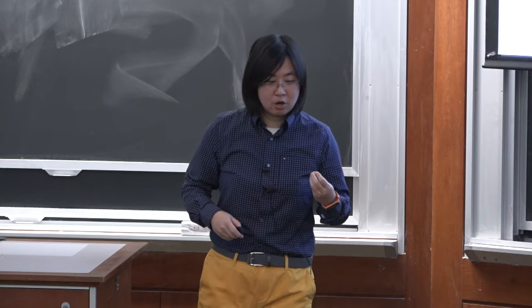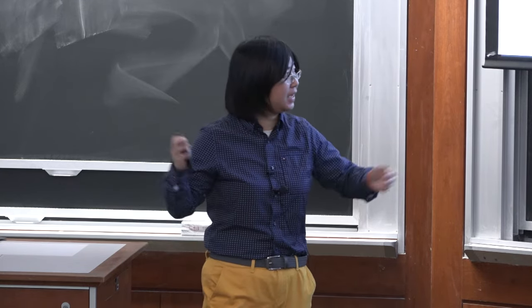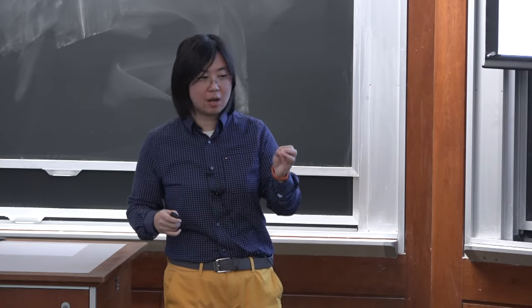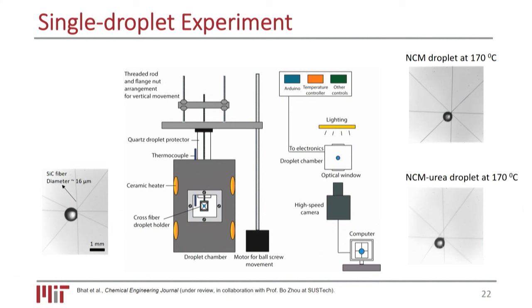And in order to understand that, we go back, stay away from the lab scale big experiments and try to look at what happens to a single droplet inside the chamber. Remember, I said in the precursor stage, we spray the droplet into a chamber and control its heating process. So we mimic this heating process by using this chamber. Inside this hot chamber, we can control the environment, and we have a holder where we put, I'm not sure if you can see it in the back, very, very thin silicon carbide fibers, and suspend our droplet precursors onto it. Then after we lower the holder into the heating environment, we can do high-speed camera imaging and try to look at what happens as the droplet evaporates.